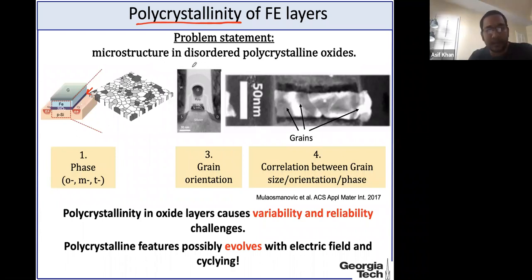And if I think about a normal, regular transistor, for example, a 28 nanometer node transistor, it probably has a length of 36 nanometers and a width of maybe between 20 nanometers to 50 nanometers. So if I do the calculation, the number of grains that we can have in a transistor probably ranges between 20 to 100.